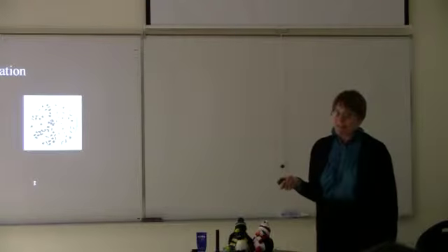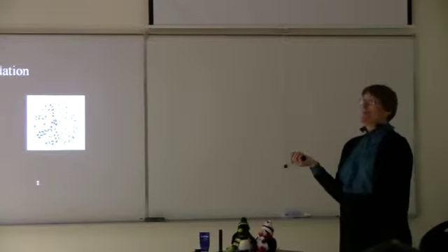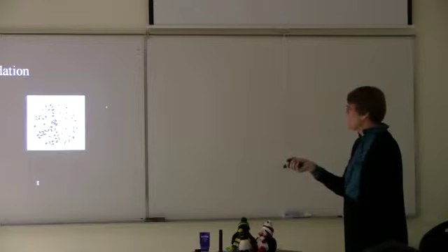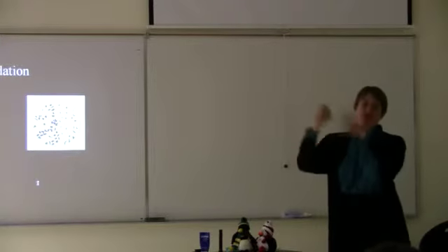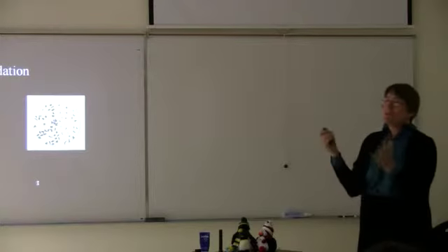The first problem we had when we started doing this was, well, how do we validate this? How do we prove that what we're getting on this computer method matches the ways other people do it? So we couldn't find any porosity standards. They just didn't exist. So we were trying to find something where we could measure it and confirm the two methods. What we finally found in the back of the geology book, these circles that were used for field geologists to estimate things in the field, not necessarily porosity, but if you look at it, it has about this distribution, it's 35% or 20%. So we thought, okay, this is good enough. And so we used the given values out of the book.